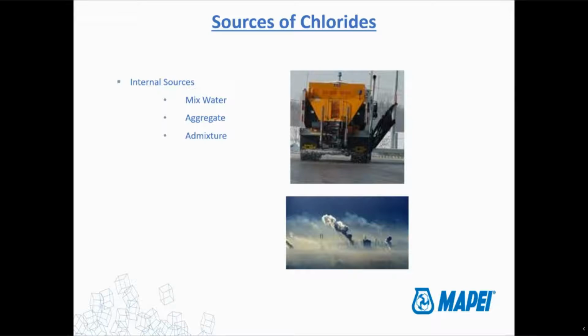But that's why it's always good in your specification to say that they should be using cleaned aggregate. You always want to wash off the aggregate before you use it, and that's mainly because you don't know where it's been stored. It could have been accumulating chlorides while it was sitting wherever it was. And those chlorides, if you introduce them right at the beginning, are going to just speed up the time until corrosion starts to actually happen.